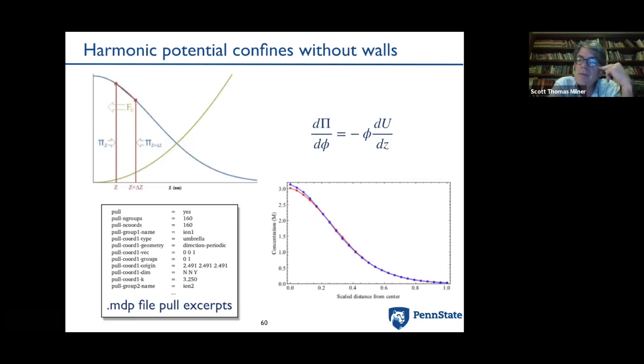And so if you want to be able to simulate things like that and be realistic about it, then you need to be sure that your interactions between the ions and the water under those strong concentrations are reasonable. And you remember how OPLS was called that because it's the optimized potential for liquid simulations, and what they did was to adjust the interactions in such a way that they got sensible liquid behavior, sensible densities, sensible boiling points and things like that. Basically, sensible equations of state for the liquids.